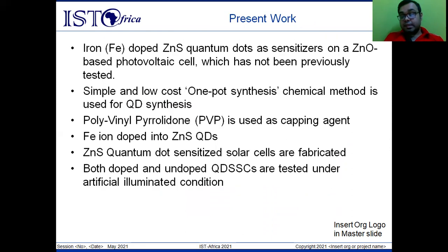Now, for our present work, we will consider zinc sulfide quantum dots. We'll dope them with iron, which is one of the transition metals, and fabricate solar cells using both the undoped as well as the iron doped zinc sulfide quantum dots, and test them under similar conditions. We will see if there is an increase in efficiency, and if there is, how much is the increase? Is it even significant?